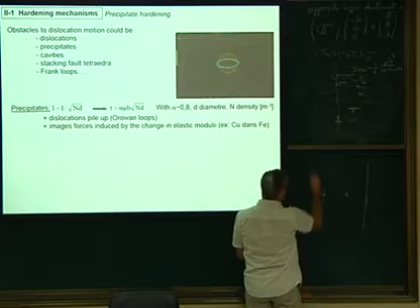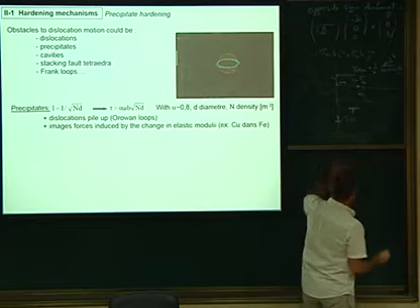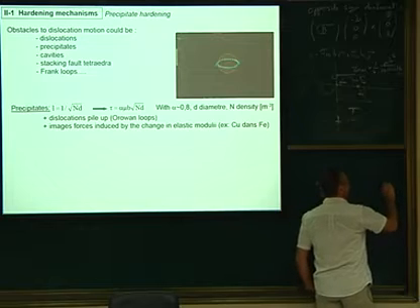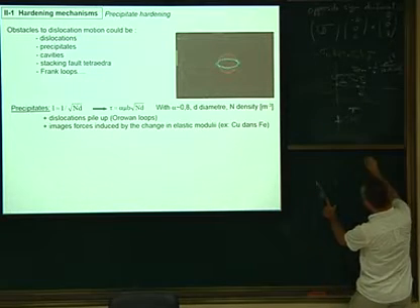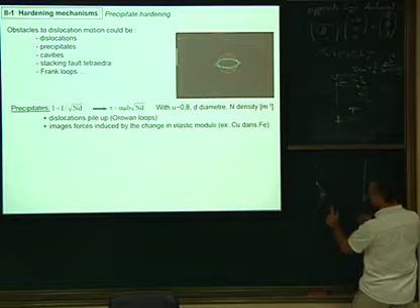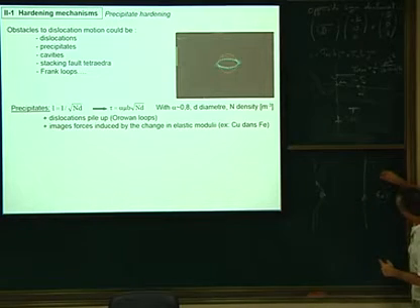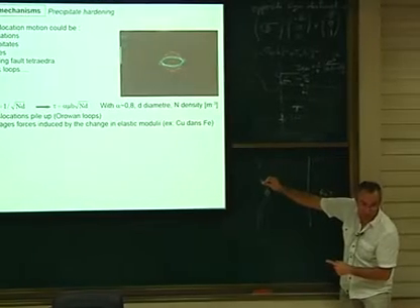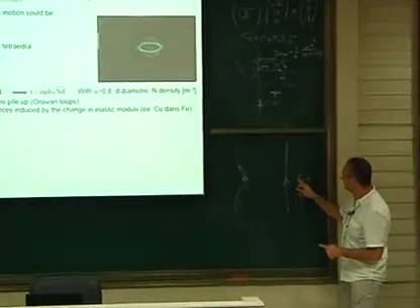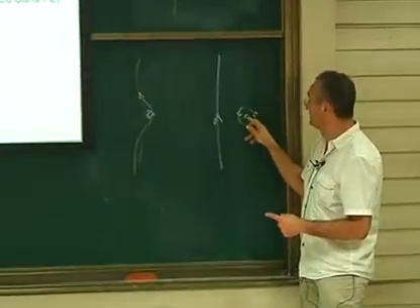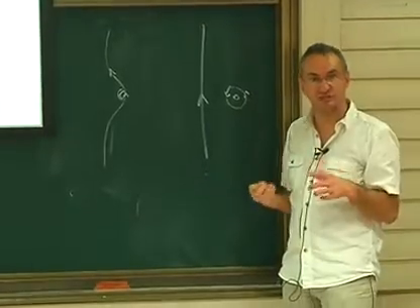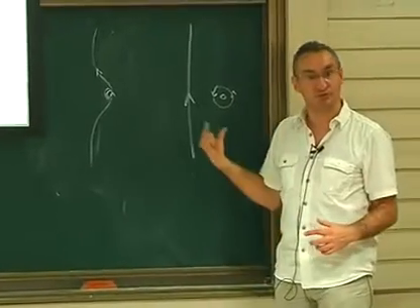At the end of the day, when it has crossed the particle, you will have your residual dislocation, which is that one here, and my dislocation, which has left, is like this. I applied the shear so that it moves from right to left. It means that this one will move to the right and this one will move to the left. So it means that this particle is sheared. You see, it wants to be sheared.